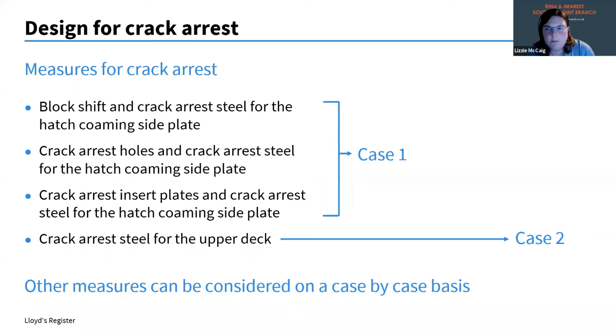And then where you've got the crack going into the parent material itself, that's where you use crack arrest steel. You don't really want your crack initiating in your weld and then deviating into the plate and going all the way through the plate, causing lots of brittle fracture. So you can use crack arrest steel. And these measures have been extensively tested, mostly in Japan. That's why IACS has included these as example measures in their unified requirement, although it's important to note that these are only possible measures. You can do other things, but it's a bit more complicated to demonstrate they work.